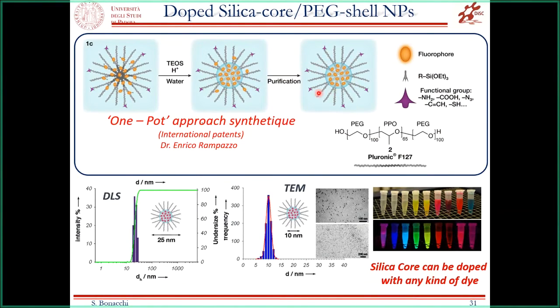dye-doped silica nanoparticles and then obtain very highly stable, water-soluble nanoparticles that, even if, as I said, they are no longer atomically precise, are in any case characterized by a very narrow distribution, as you can clearly see here by looking at the dynamic light scattering analysis and TEM analysis. And particularly by combining these two morphological analyses, we can estimate an average hydrodynamic diameter of around 25 nanometers and a silica core of about 10 nanometers.